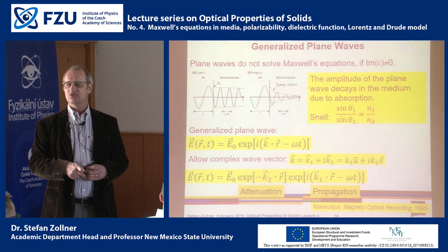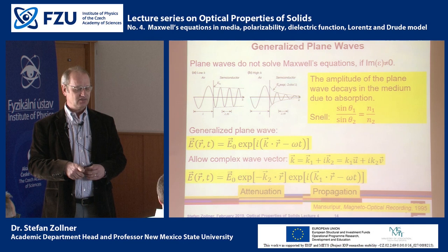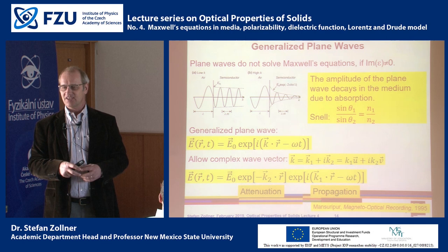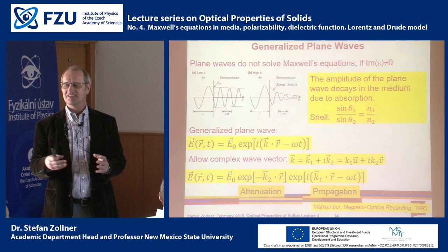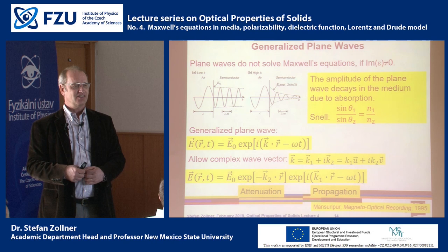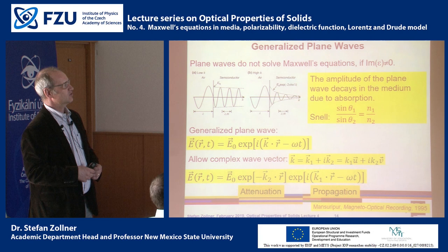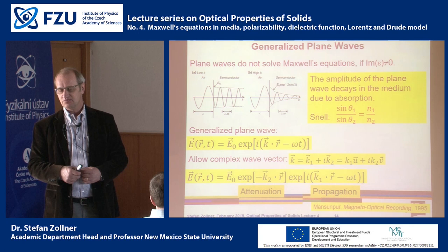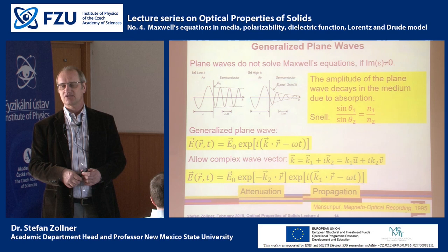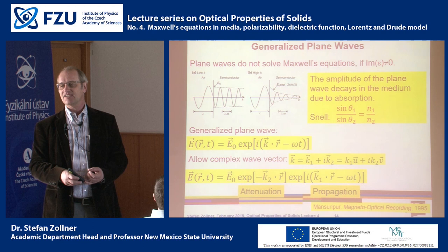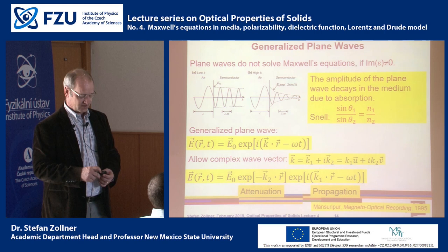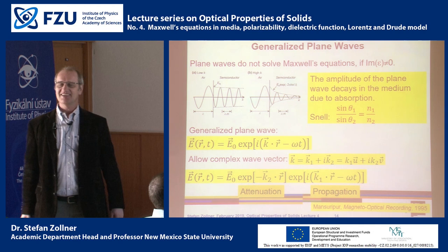These anisotropy effects are usually larger in the infrared spectral region than in the visible. If you take a slightly distorted perovskite structure, it looks perfectly isotropic in the visible and in the UV, but then you go to the infrared, and the anisotropy effects become much larger. And in the field of exploring the anisotropies for low symmetry crystals, like triclinic crystals, monoclinic crystals, you find very recent papers in the last 5 years which explore this. So yes, I can only agree with you that this is confusing, but I cannot show you a simple picture.